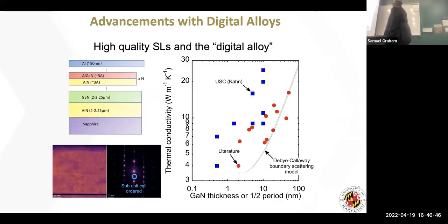So this is the interesting thing. If you have a superlattice structure, this is showing you the gallium nitride thickness. I'll show you the picture on the next slide. So this is the gallium nitride thickness of the half period. If I have gallium nitride and aluminum nitride, say the total thickness is 10 microns, then my half thickness would be 5. Or if I have, say, 1 nanometer of GaN and 3 of aluminum nitride, my half thickness would be 2. What it shows is that if I do a superlattice, it's out here, but if I do the digital alloys, you can see that the thermal conductivity is rising much faster.